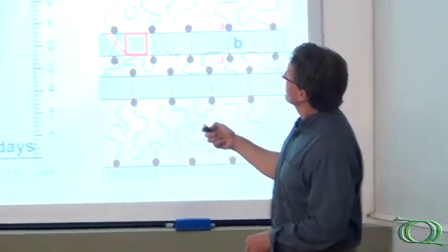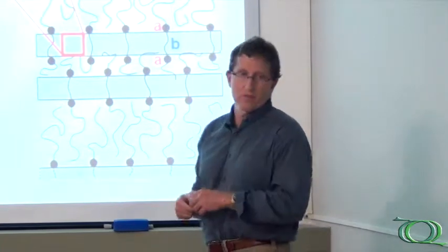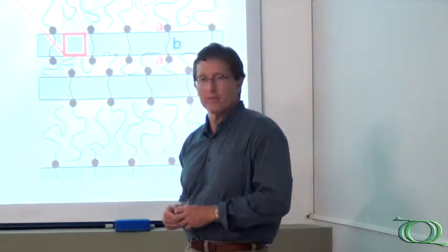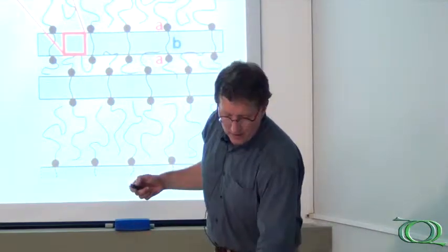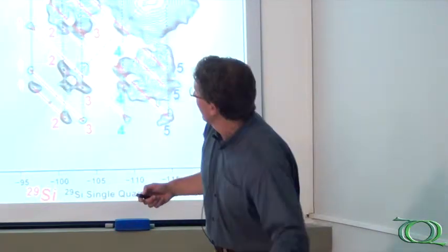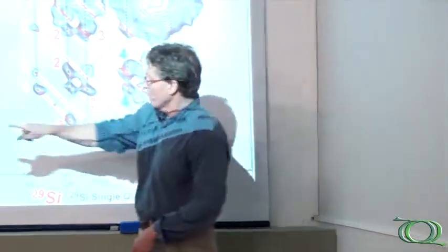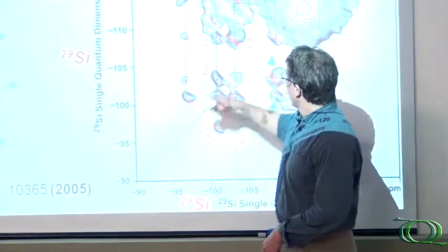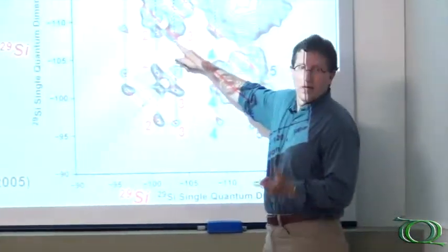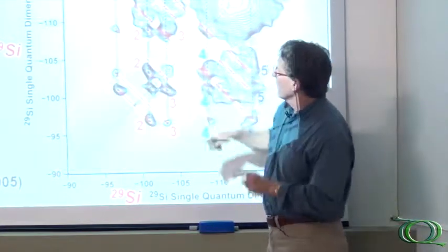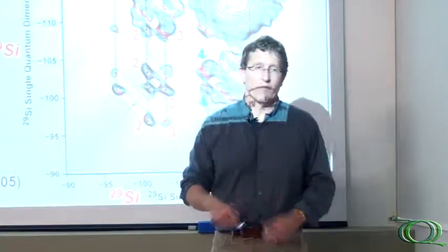Well, so this I think took approximately 12 hours, maybe 18, not so long. The one thing I will say about the J-coupled experiments, and maybe this is for just those, Helmut and Tiago, is that this particular experiment with Darren Brower and Malcolm Levitt is a dipole coupling, and they can do this on natural abundance samples. But it's not through bond. The J-couplings turn out to be more informative because they're directly through bond, and those require isotopic enrichment.